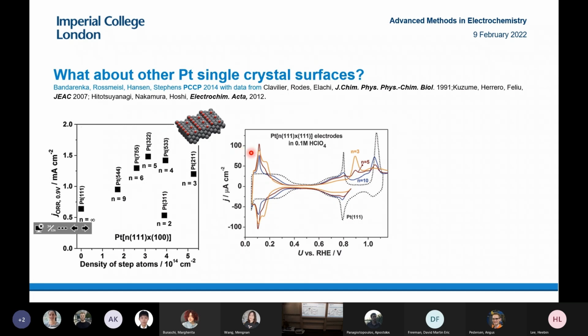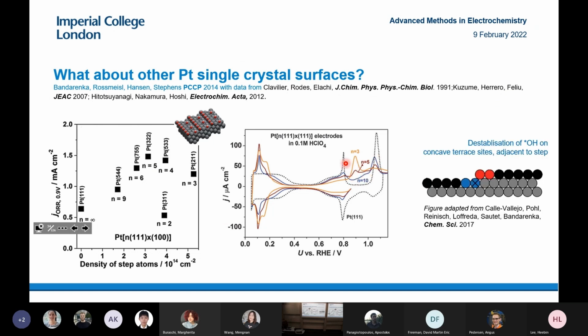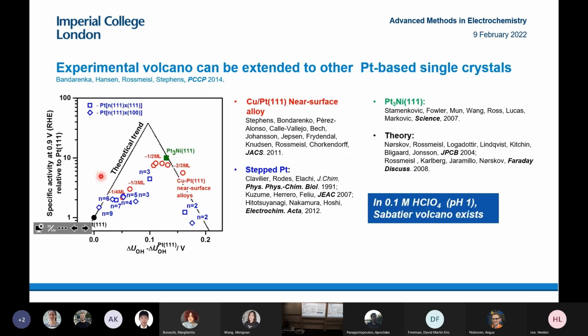And that's the peak you see in this region, what's usually called the hydrogen underpotential deposition region. I think it's probably not hydrogen. But then you actually destabilize OH at the terraces, and this is very similar to the effect of alloying. So we quantified the shift in these different step surfaces, and what we found is that they all follow the same trend as the near surface alloy. We also put in the most active catalyst for oxygen reduction, which is the platinum 3 nickel single crystal.